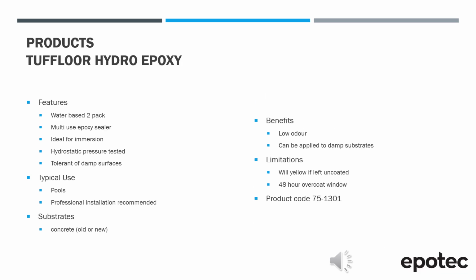Hydro Epoxy is our priming solution for pools with hydrostatic pressure or damp surfaces. Hydro Epoxy is hydrostatic pressure tested, exceeding 45 psi or 310 kPa. It is also negative hydrostatic pressure tested and water vapor transmission rate tested. The TDS details the testing data.